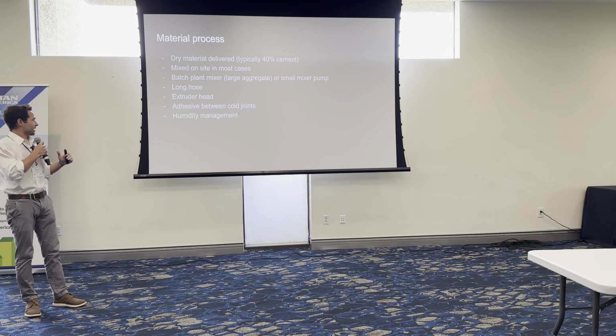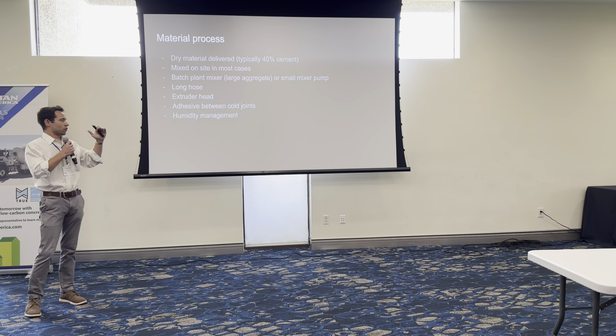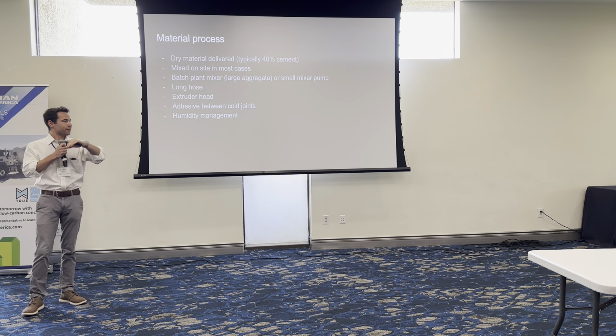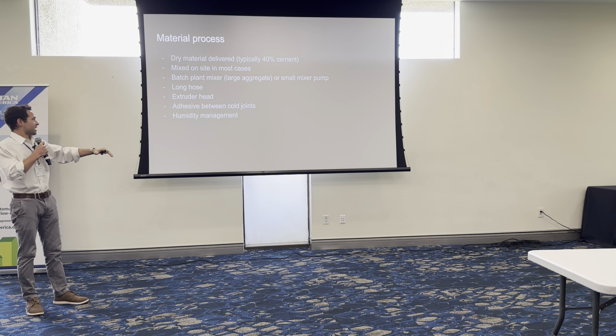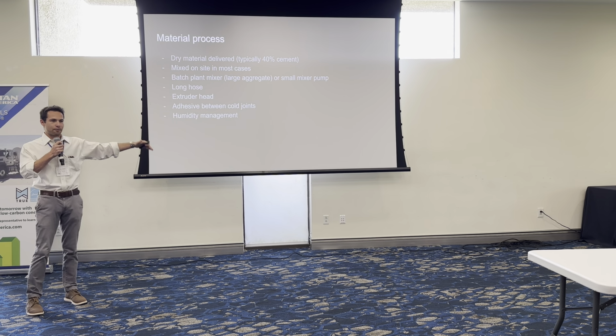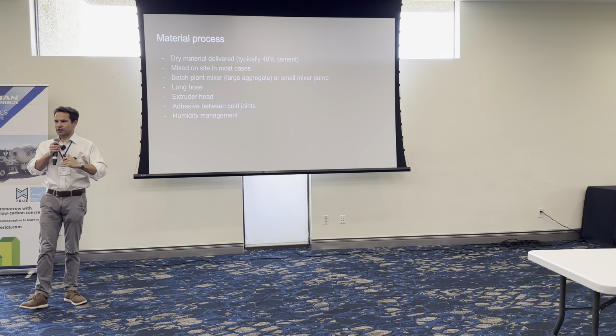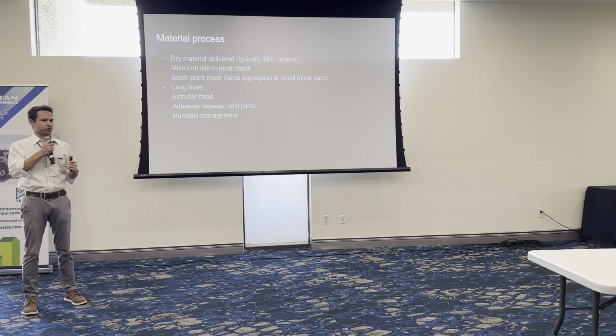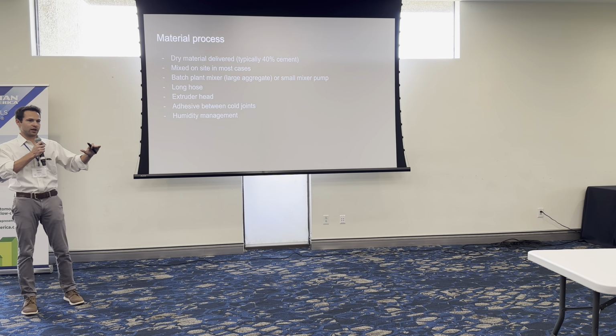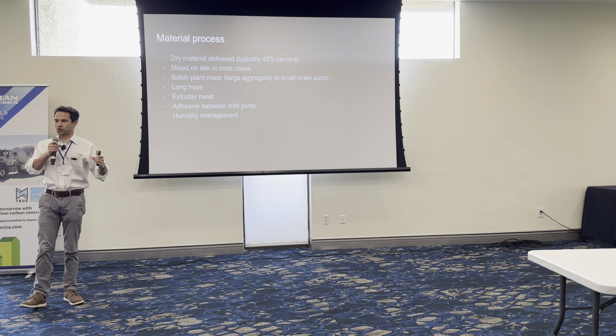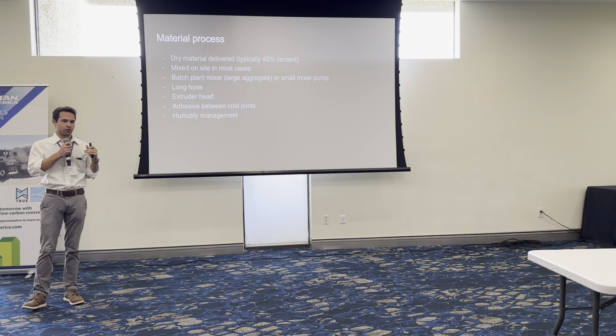From the hose, it gets to the extruder head, which lays the concrete layer by layer with an adhesive between cold joints. So if you stop printing for the day and you want to start the next day, typically for a large gantry system, they might print between 1 and 3 feet in a day. You can't have a cold joint because that'll create cracks. It'll prevent it from being a monolithic structure.